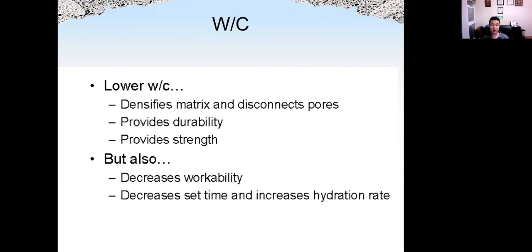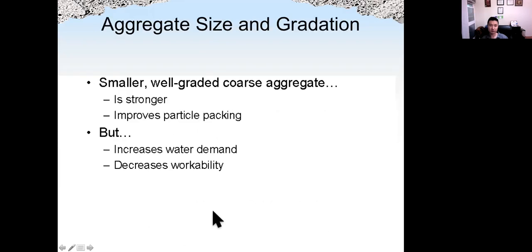Look at water cement ratio. If we reduce the water cement ratio, we can densify the matrix and disconnect the pores. That's good, because it will provide durability by reducing the porosity. It will also increase the strength. But it will also decrease the workability, decrease the setting time, and increase the hydration heat. And also potentially increase the autogenous shrinkage.